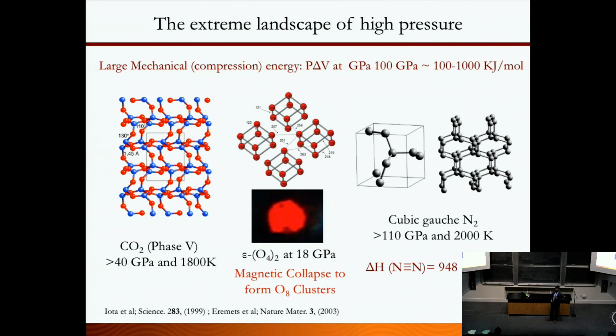Carbon dioxide starts with double bonds, right? But here you have a four-fold coordinated extended structure, like a 3D network structure. So when you apply pressure, you increase the coordination, you increase the valence of the material. It's the same if you look at oxygen, which forms this beautiful scarlet red color. It makes these O8 clusters under pressure.